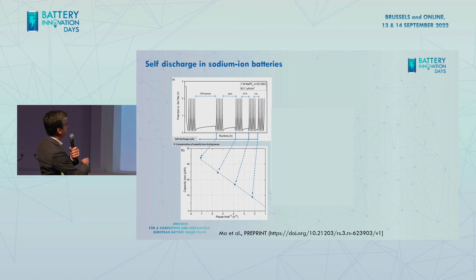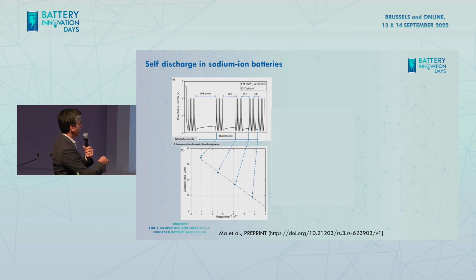We started from 50 hours to lower pause time of 5 hours. And if you plot this pause time versus capacity loss, then you can see that there is actually a linear relation between the square root of pause time and the capacity loss. So this tells us that this loss is diffusion dependent. So when you have a square root of time, it's often diffusion.